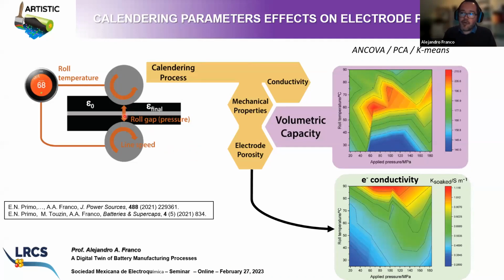of parameters. You can control the gap between the rolls pressing the electrodes. This gap is related to the pressure that you apply to the electrodes. You can control the speed of the rolls, and you can also control the temperature of the rolls. These three parameters are going to impact the final electrode microstructure upon calendering. And here I'm showing an example.